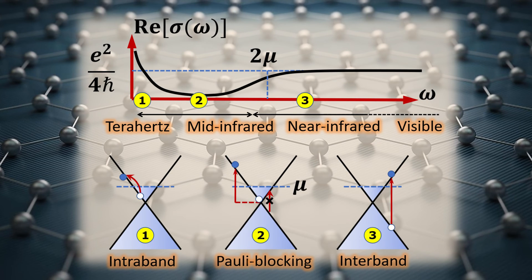At the intermediate frequency regime 2, the photon energy is insufficient to produce a direct transition due to Pauli-blocking processes, and exhibits suppressed intraband transitions, thus leading to suppressed optical response.